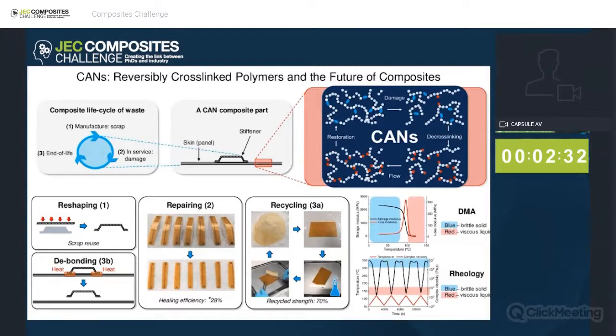So if we look at the bottom right of the slide, we can see the thermal behavior of one of the CANs, thermally activated ones that I made during my PhD. So looking at the DMA, we can see the black curve. At low temperatures, we're dealing with a 2 to 3 gigapascal modulus, so not unlike a conventional epoxy. But as this one is heated up past 100 degrees or so, it goes through a glass transition and straight into a melt. So what you end up with is a liquid with no modulus at all.